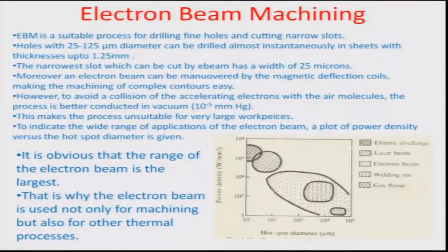Let's look at some of these different processes around the hotspot diameter that they may generate and the power density that we are talking about. So, we can think of electric discharge in the very left corner of this particular plot here. The hotspot diameters are typically in the range of about 10 microns, and the power density goes as high as about 10 to the power of 7 watt per millimeter square. The lasers again would give a hotspot of between 10 and 100 micrometers, hotspot size is more, and power density is slightly lower. It is probably in the range of somewhere around 10 to the power of 5 to 10 to the power of 7 watt per millimeter square.